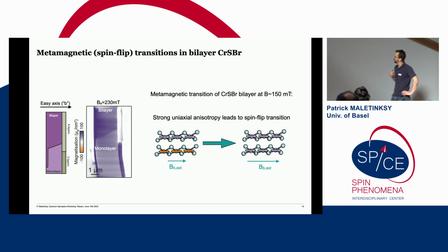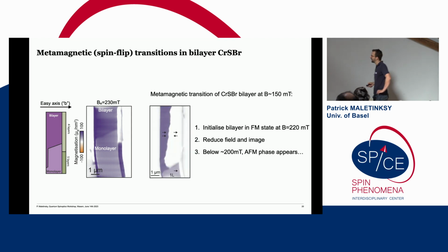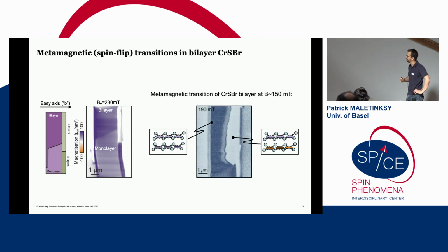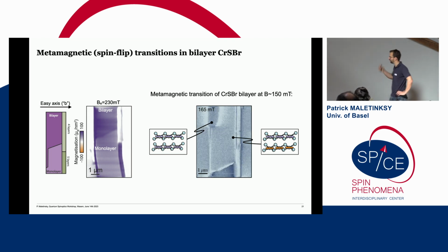So I want to show you a last set of data where we looked at this metamagnetic transition in chromium sulfur bromide that I mentioned before. This is essentially a spin flip transition where by applying a magnetic field, you turn this antiferromagnetic order to a full ferromagnet. If you look at this roughly in the transition region, you find that there is a coexistence between ferromagnetic and antiferromagnetic phases. This is again one of these quantitative images. And we can actually look at how this coexisting region or the wall that separates the two propagates as we change magnetic field. This is shown in this movie here. So it's just a sequence of images with decreasing field that shows you how this phase propagates through the bilayer.